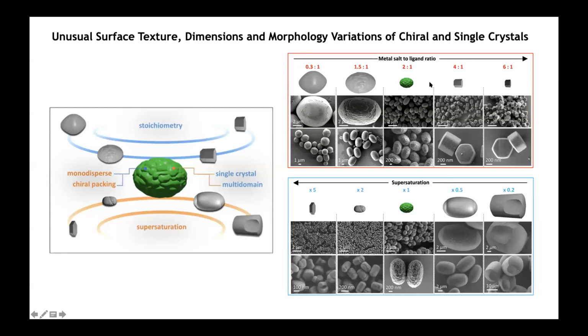When we change the metal salt to ligand ratio, only at a 2-to-1 ratio, we see these weird crystals with this strange morphology. And also when we change the supersaturation, you see the surface texture is changing, but the uniformity is very high. Also, we see here that the size of the crystals is changing a lot.